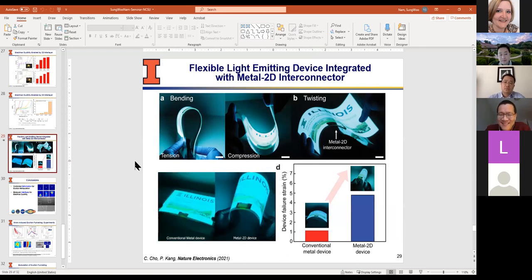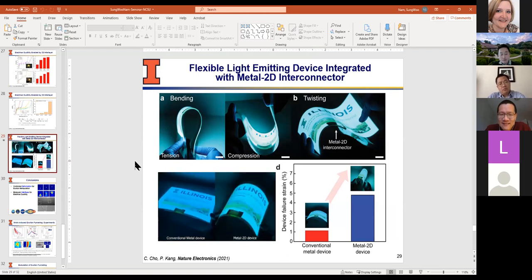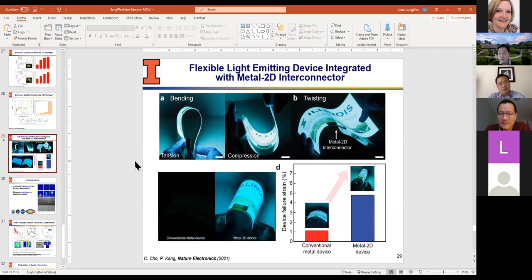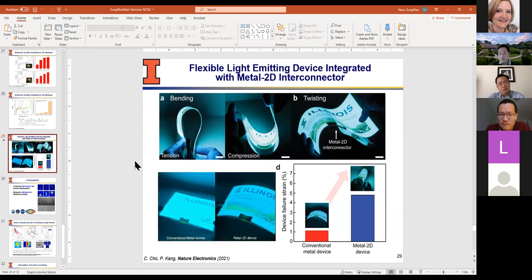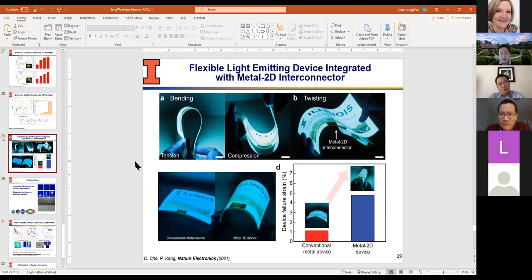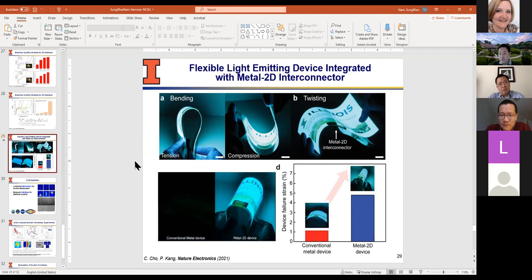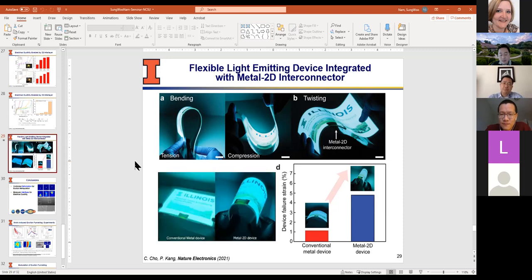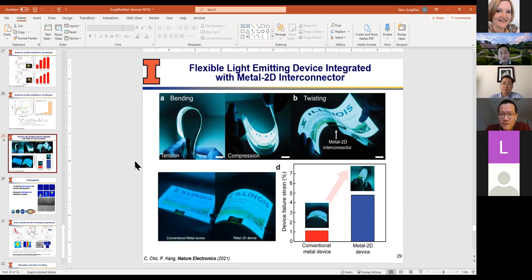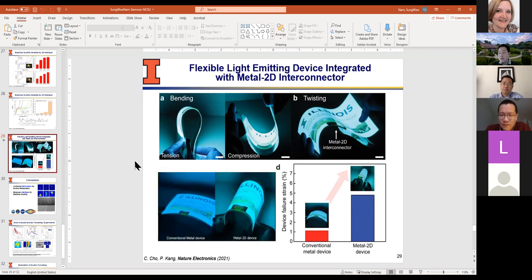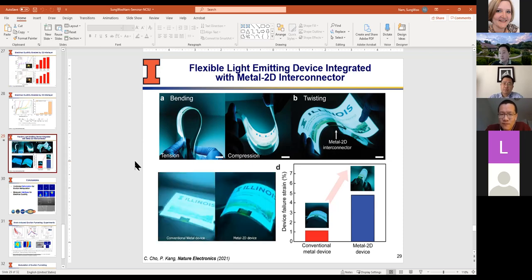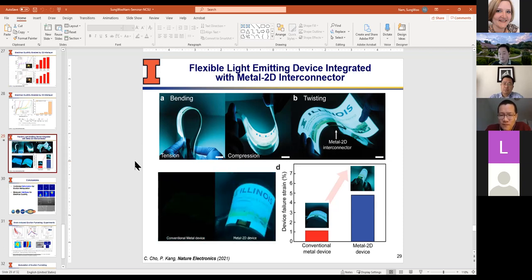We haven't characterized the microscopy or electron microscope images of the compression, but we did look at the adhesion of graphene-gold versus just titanium-gold, for example, on PDMS. We did the traditional testing with a tape test and MD simulation to help us look at adhesion energy. It turns out, and that's one point we made in the paper, that the adhesion level happens to be in the right spot. It's a little lower than titanium-gold, but not substantially lower. When you don't have titanium, it's just gold, and the delamination is severe because adhesion is not very good between gold and the PDMS substrate.